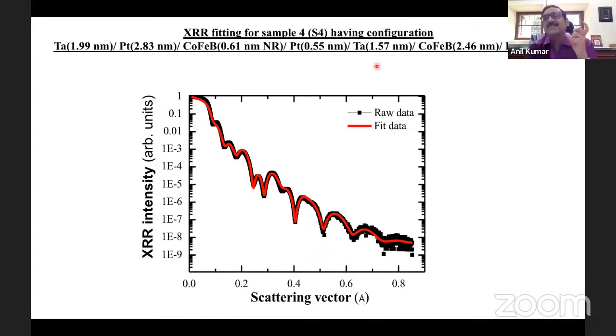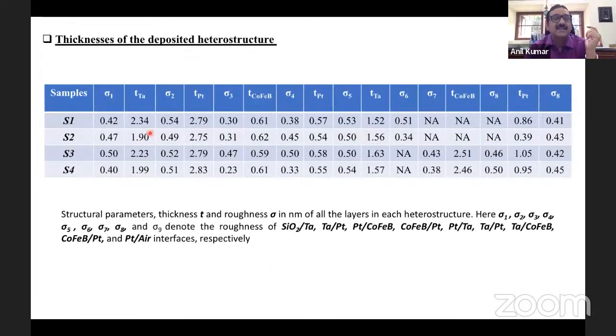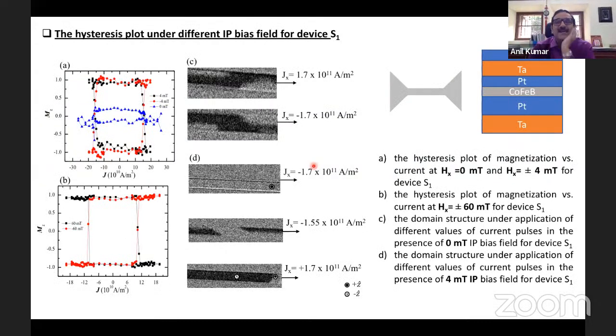So for every film which I'm going to discuss, we have done this X-ray reflectivity, and you can extract a lot of parameters from X-ray reflectivity. The thickness of the individual layers, the interface roughness. The interface roughness should be extremely small to see this kind of effects. You saw, I am just talking about 0.3, 0.4, 0.5 nanometers. That means 3, 4, 5 angstroms of a layer. And if the surface roughness is much more than that, it can destroy the properties. Now, let us look at this structure.